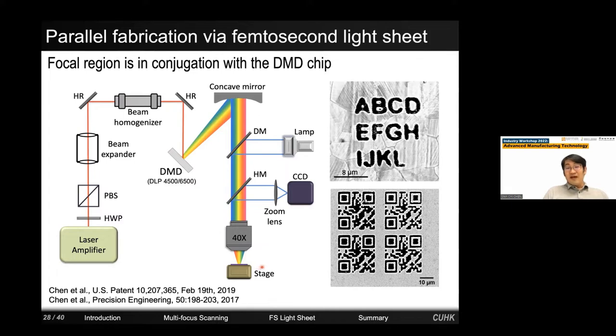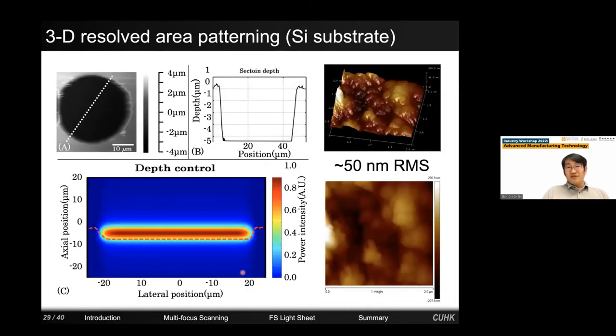And next, by axially moving the focal plane or light sheet around, and by changing the pattern accordingly, we can create arbitrary structures at high speed. This slide shows a simulation of the intensity profile of the light sheet. You can see it has a thickness of around a few microns. It's extremely flat. So by just moving the light sheet around, we can drill flat-bottom holes, which reach a 50 nanometer surface roughness on a silicon substrate.